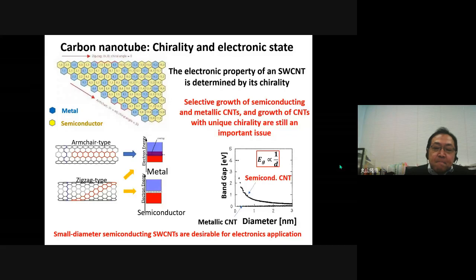Depending on its chirality, a carbon nanotube can be both metal and semiconductor. That is, the electronic property of a carbon nanotube is determined by its chirality. Also, the band gap of semiconducting SWCNT is inversely proportional to its diameter. Stochastically, 1/3 of grown SWCNTs are metallic, while the others are semiconducting. However, selective growth of semiconducting and metallic carbon nanotubes is not realized yet. This impedes realization of carbon nanotube electronic devices.